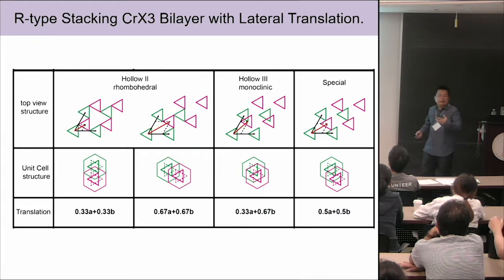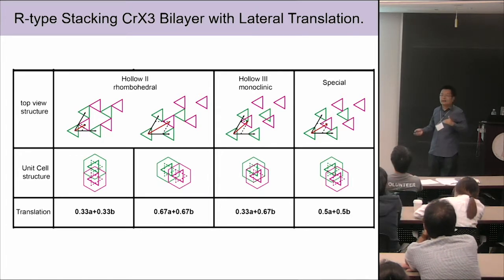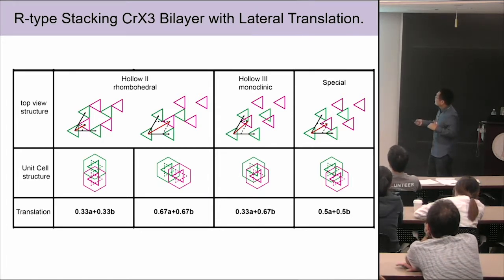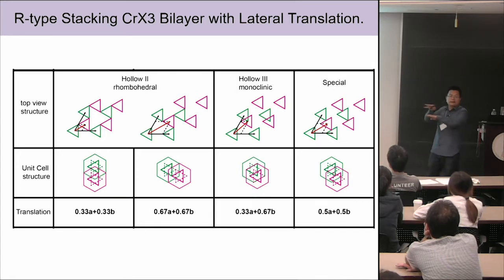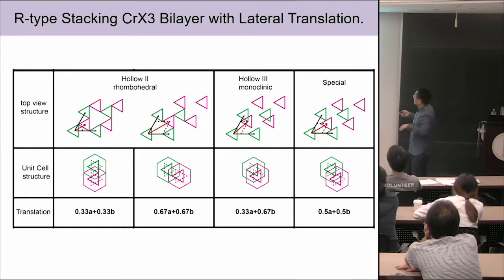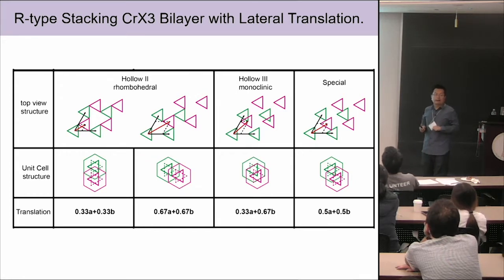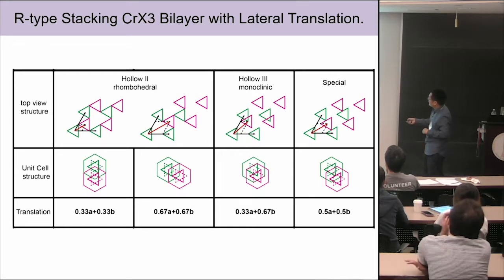Then if you add another layer, now I have a bilayer system. So this pink color represents the top layer structure, and the green one represents the bottom layer. Now, these top and bottom triangles can have a relative shift, okay? They have the same orientation, but they can have a relative shift. These shifts give us these so-called R-type stacking structures for the bilayer chromium triiodides. And the middle row here is the unit structure from this bilayer. You can see how these shifts happen, right?